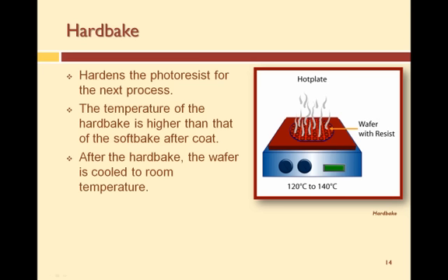However, too high of a temperature in a hardbake could cause the photoresist to re-flow, which would destroy the pattern. Therefore, it is important to keep the temperature and time of the hardbake within specifications.